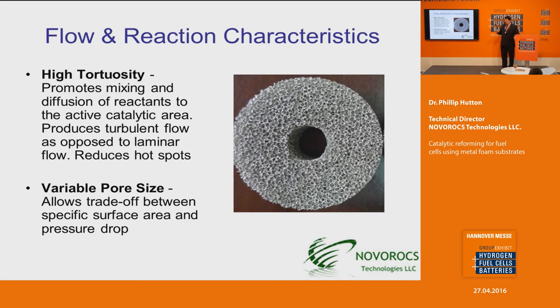Flow and reaction characteristics. As you can see, a typical metallic foam has high tortuosity. What this means is, the definition is tortuous path. So this means that there's not a well-defined path. This promotes mixing and diffusion of reactants to the catalytic area. It produces turbulent flow as opposed to laminar flow, and that's good for heat transfer. So it reduces hot spots or cold spots, depending on whether your reaction is endothermic or exothermic.